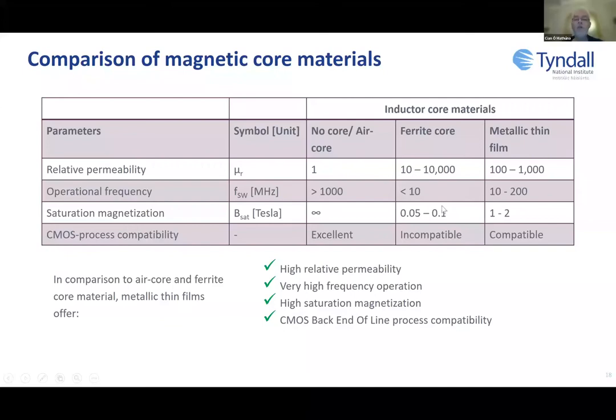The other thing that is really important is, in fact, the ferrite core will only work up to a certain current level, at which point its material properties will collapse so that the permeability will go to one, like air core. And it's very limited in terms of what's called its saturation magnetization.